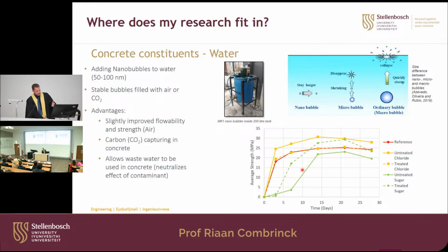And once you add the bubbles, it's this dashed line, you can see you sort of get rid of the effect that contaminant had. The retarder is not that retarded anymore, and the accelerator, due to the chloride, gets back to the reference again. So it really neutralizes that effect and opens up the door for using contaminated and waste water in concrete.